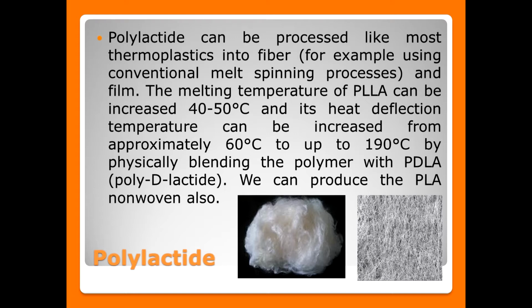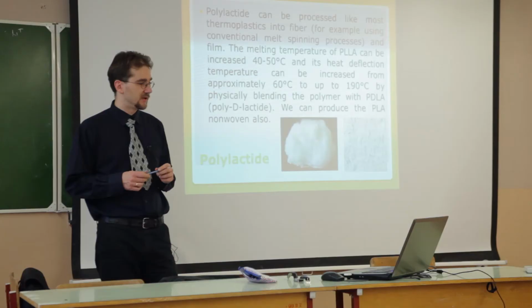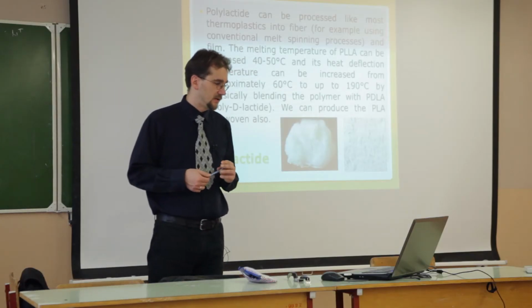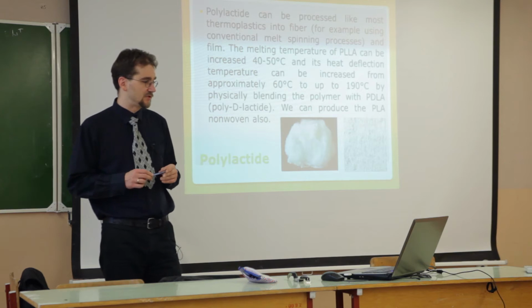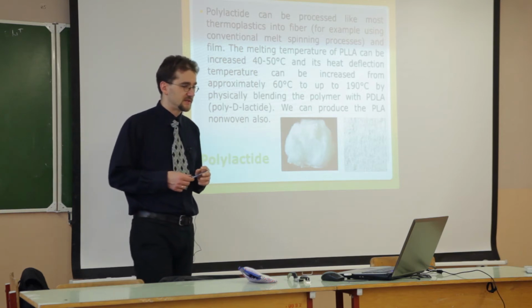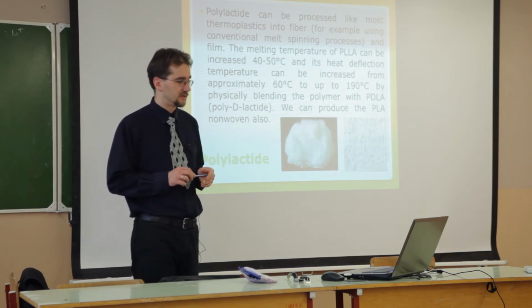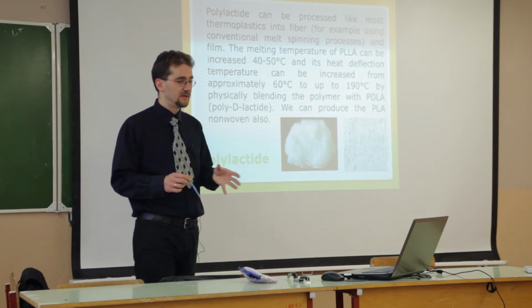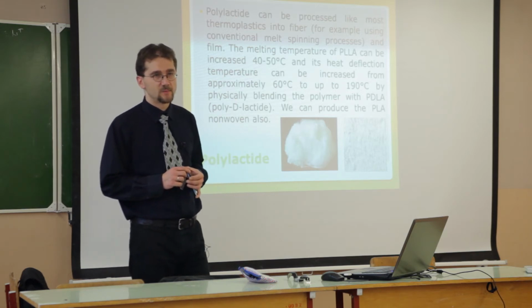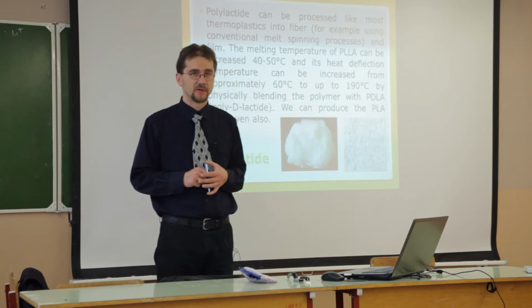We can control and change the properties of the material using a mixture of polylactide L and polylactide D. For example, the melting temperature of polylactide L can be increased by up to 50 degrees, and the heat deflection temperature can be increased from 60 degrees up to even 190 degrees by physically blending this L polymer with the D form of the polymer.